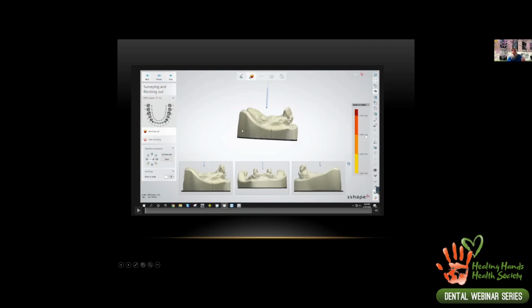And each software has its own color coding. For this specific software, it starts from yellow, goes to orange and red. But what these numbers mean: if you look at the line between the yellow and the orange, that's 0.25 millimeters, 1/4 of a millimeter, which is exactly the 0.010 inch undercut depth that we use in a lot of the conventional cast clasp assemblies. The second line that you're going to see is 0.50, half a millimeter. That line corresponds to a 0.020 inch undercut, which is mostly what we use for ring clasp assemblies or rolled wire, more flexible clasp assemblies.